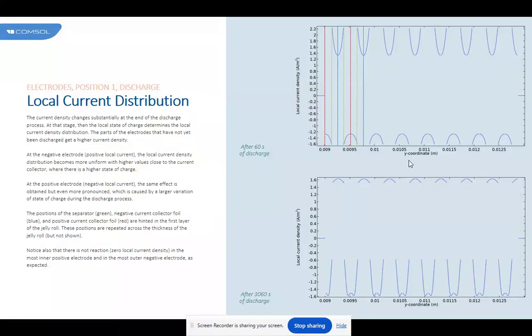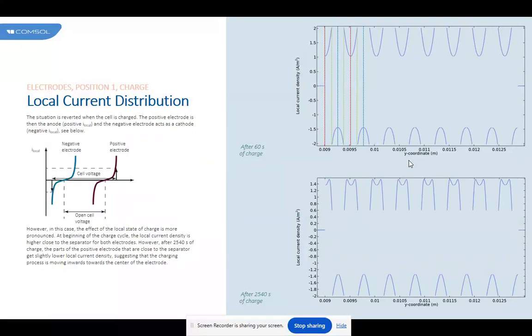At the positive electrode, negative local current, the same effect is obtained, but even more pronounced, which is caused by a larger variation of the state of charge during the discharge process. The positions of the separator in green, negative current collector foil in blue, and the positive current collector foil in red are hinted in the first layer of the jelly roll. These positions are repeated across the thickness of the jelly roll but not shown here. Notice also that there is no reaction, zero local current density, in the most inner positive electrode and in the most outer negative electrode, as expected.